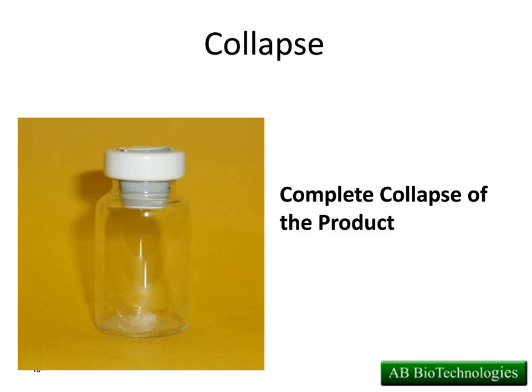Additionally, this is going to trap moisture a lot more than a nicely freeze-dried product. So, in a good cake, we might be getting down to less than 1%. In something like this, who knows? You could be at 10, 20% moisture because it's just very difficult to get out. Reconstitution could be terrible. This is what we call a vacuum-dried glass, in contrast to a nice freeze-dried cake. So it may take you 30 minutes to shake and reconstitute this. So this is something we want to definitely avoid during freeze drying.